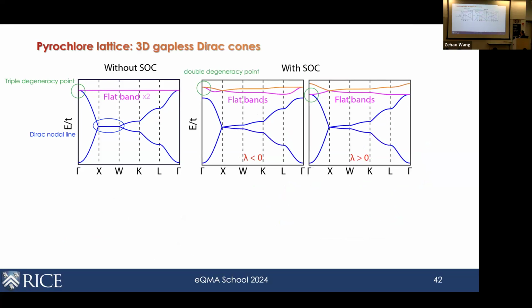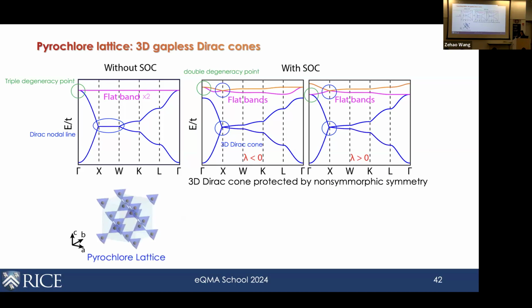The other interesting thing is that this spin-orbit coupling gaps out the nodal line along XW everywhere except strictly at the X point. If you look at the X point, the bands are still stuck together. This remains gapless in the presence of spin-orbit coupling, and there's a reason for this. The reason is this so-called non-symmorphic symmetry. How do you see the non-symmorphic symmetry?